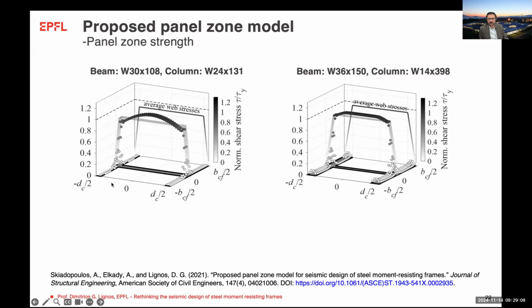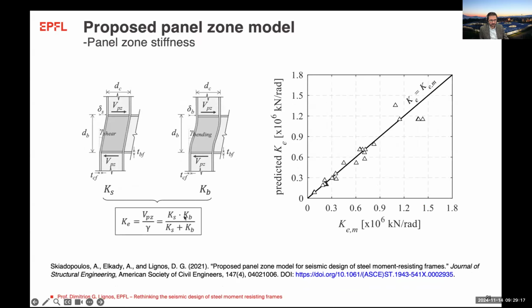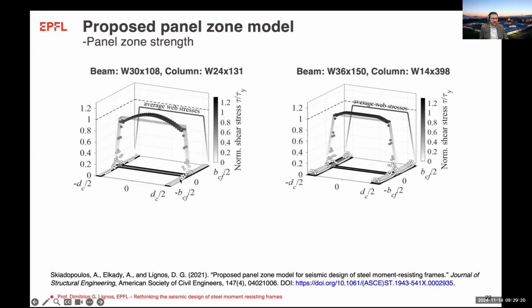And what happens here is that in columns where the flanges are not relatively thick, if you look at the flange contribution, you see that it is fairly minor. But if I'm looking at columns where the thicknesses are relatively high, you see that in this case the flange contribution to strength starts to be very important.